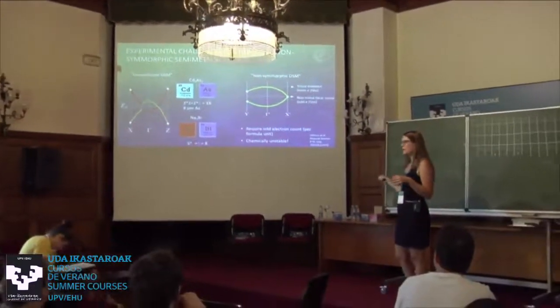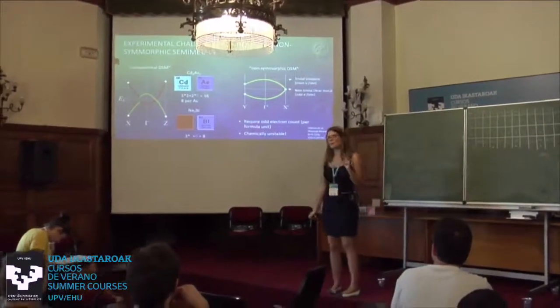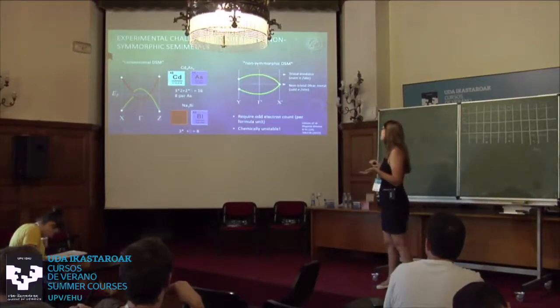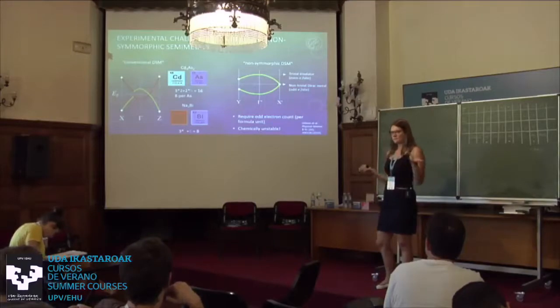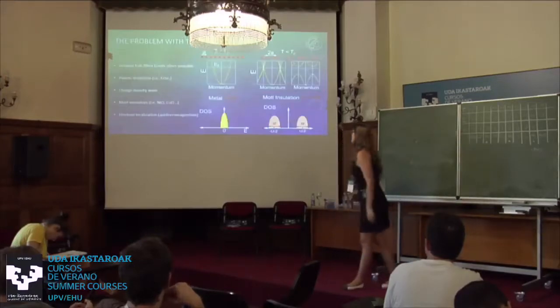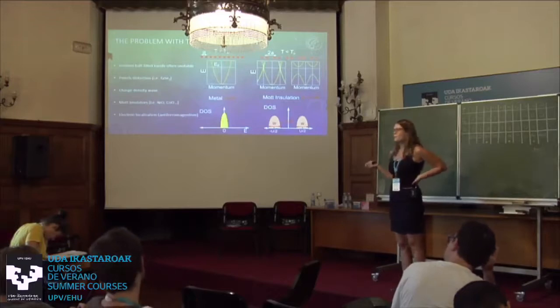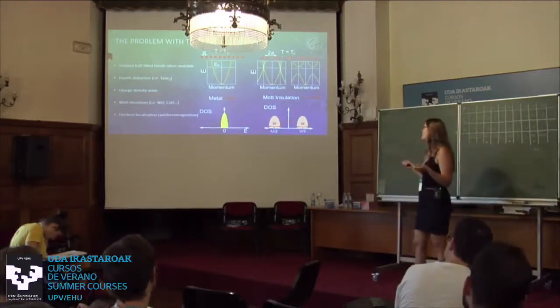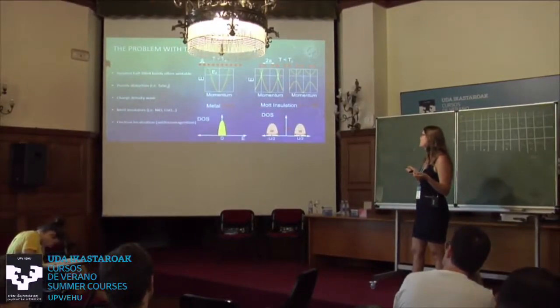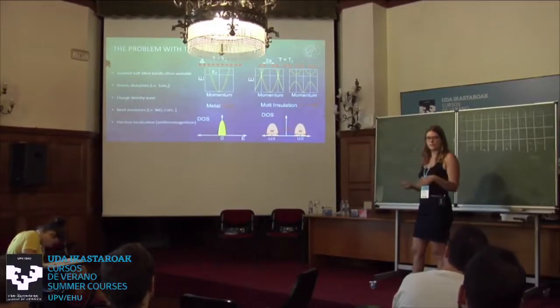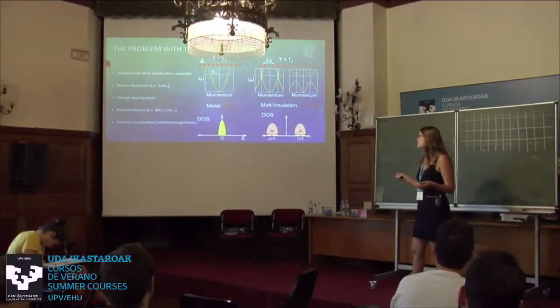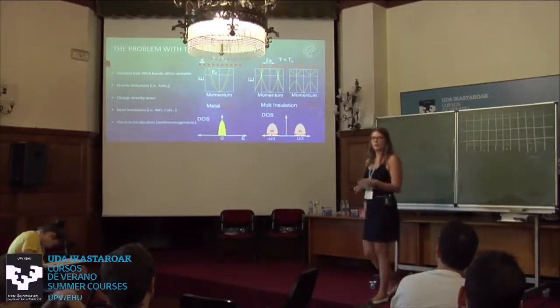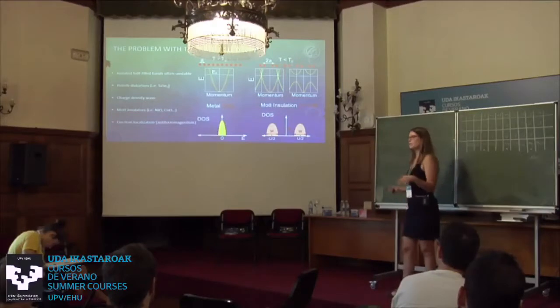So if we want to move the Fermi level to the point we care about, we need to have a half-filled band, so 1 electron per band. And this is chemically extremely unstable. And actually, even worse, if you want it to be isolated, so if you don't want any other pockets to cross, then there are lots of different mechanisms compounds like to use to avoid this kind of isolated half-filled band. And so you might be familiar with some of them. What happens to compounds where there's an isolated half-filled band is that they like to undergo Peierls distortions or charge density waves, where they distort the lattice to actually reduce this kind of crossing and gap out, or they like to be Mott insulators, which does the same trick, so the crossing we care about gets gapped and it's not there anymore. Okay. So we need to find a trick to get around that.